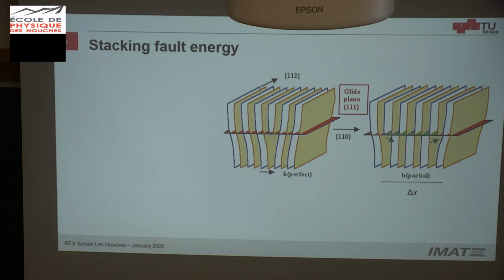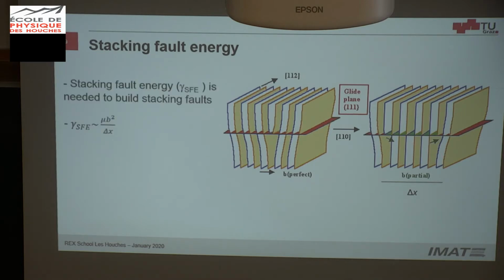The larger this distance is, the more stable the stacking fault is. And it means the larger this distance is, the lower the energy you have for forming stacking faults. So it's a very simplified interpretation of stacking faults and stacking fault energies. But basically, if the stacking fault energy is very high, which means this is very small, the partial dislocations can reconfigure into a perfect dislocation, and the dislocation can move as before without problems. And moving of dislocations is what you need for annihilation of dislocations, and mobile dislocations are what you need for dynamic recovery.